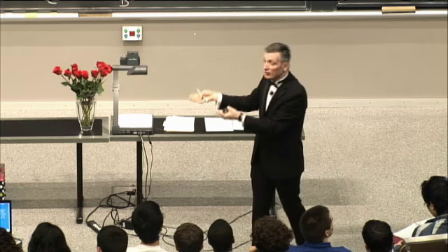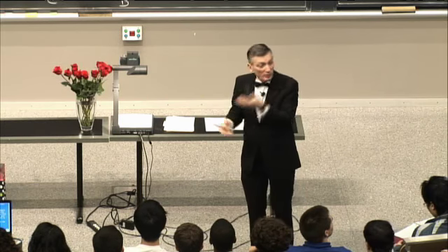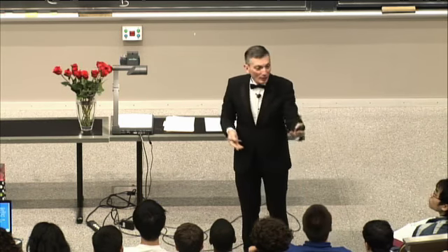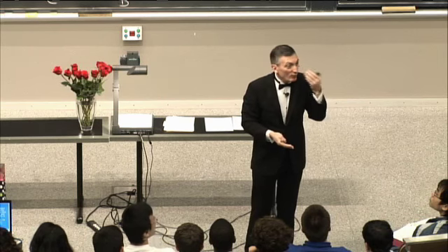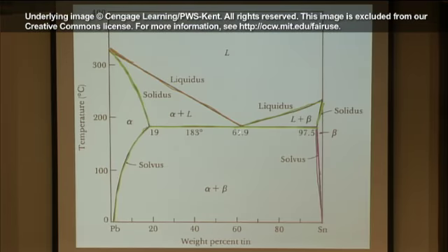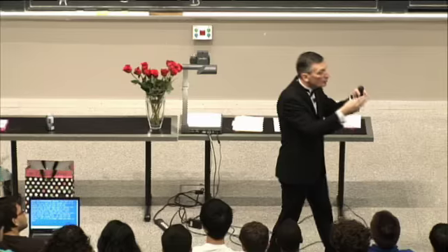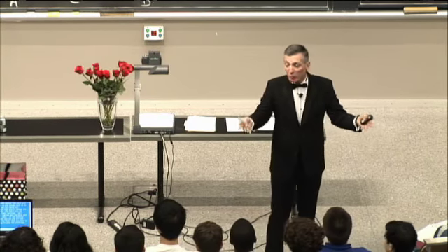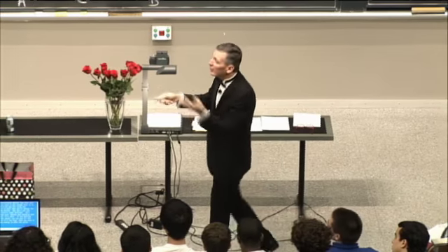So you say, well, why don't you get something that's lower melting? Well, if it's lower melting, you know from running your laptops and charging your cell phones, they get warm. So it's a Goldilocks problem. If the melting point of the solder is too low, you might encounter that temperature in service and pop all of the joints. If the melting point of the solder is too high, then you have to use so much energy to make the joints that you damage some of the microelectronic componentry. So this has to be in the right temperature range.